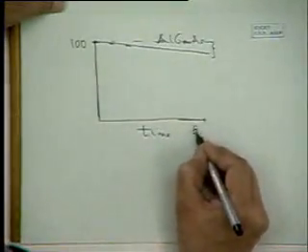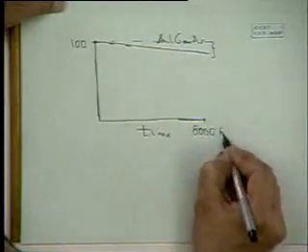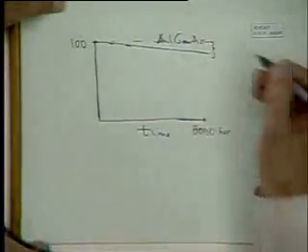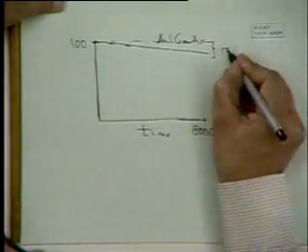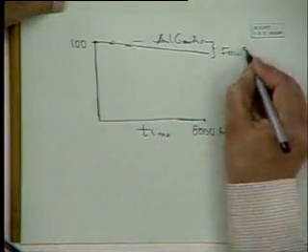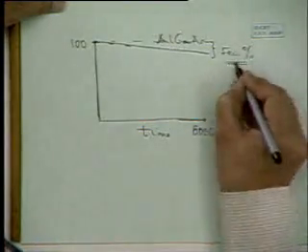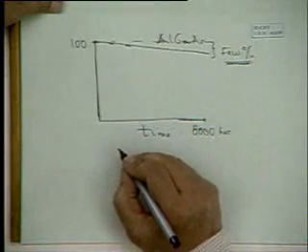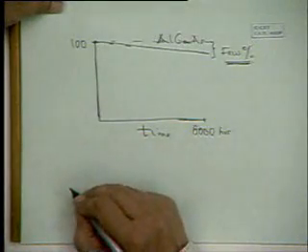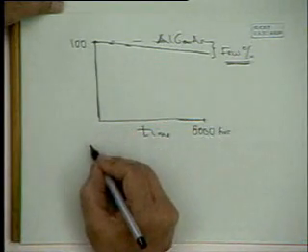So test for 8,000 hours. Typically, one tests for 8,000 or 10,000 hours. There's a degradation of only a few percent. So these are highly reliable devices.